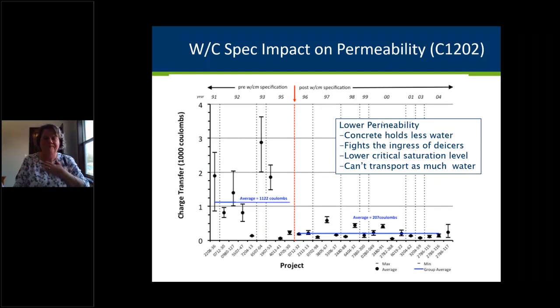How do they affect the permeability? This red dash line is the pre-water cement. On the left is the pre, on the right is the post-water cement. You can see that the permeability pre was 1122 coulombs average on our projects. Post-water cement, and keep in mind, these are 15 to 20-year-old pavement numbers, our average coulombs was 207. So really a great reduction in permeability.